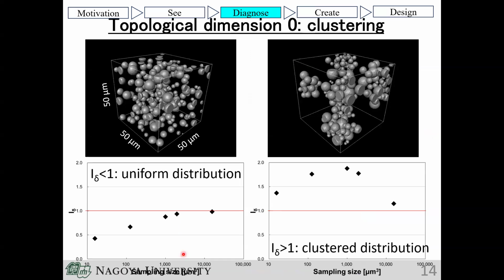This method can be extended to 3D space by partitioning the volume into cubic voxels. As shown in the provided example, the left figure yields an I delta smaller than 1. That means a uniform distribution, whereas the right figure exceeds 1, indicating particle clustering. Furthermore, a peak value of the distribution reflects the degree of localization, while the volume associated with the peak represents the cluster size.